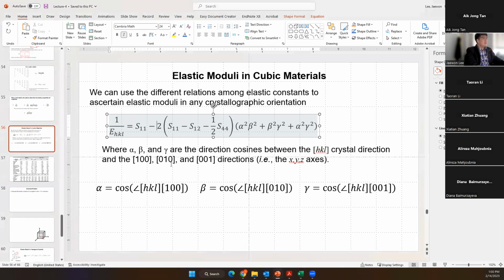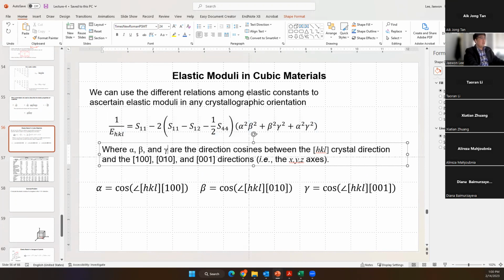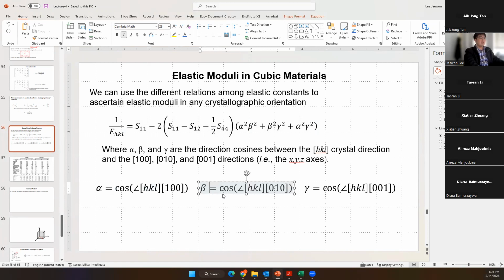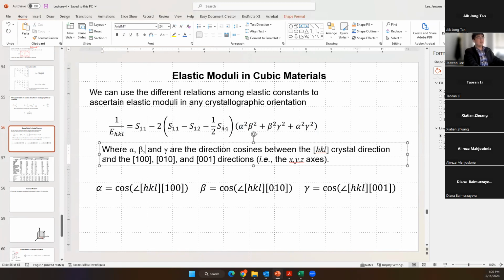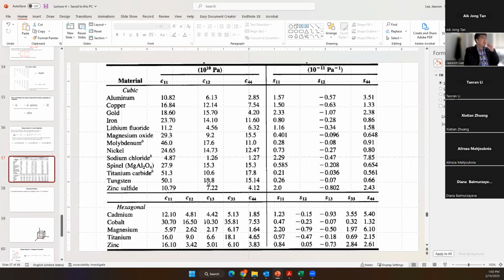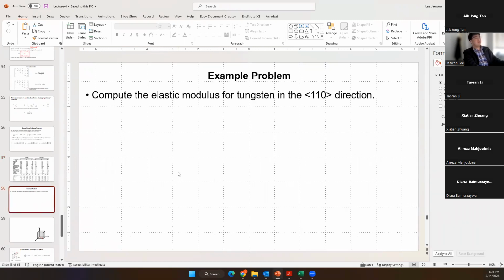Based on this matrix component, we can calculate the elastic modulus in these situations. Here, alpha indicates the cosine angle between HKL and 100, beta is the cosine between HKL and 010, and gamma between HKL and 001. So we can calculate the angle components, and then the elastic modulus. Here is an example of the tensor components C11, C12, C44 for cubic materials: aluminum, copper, gold, and others. Many engineers already calculated these, so we can use them.